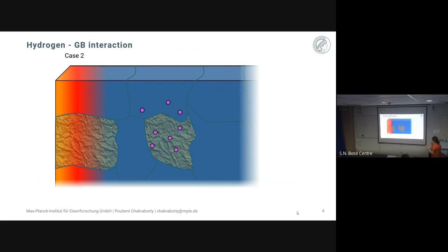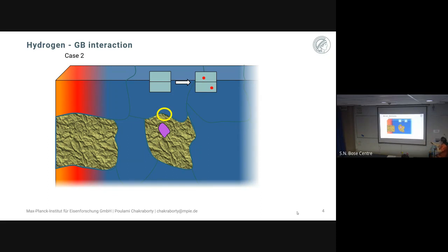Now coming to another case, let us assume that these solute atoms are dissolved in a solid solution. Then they come together and form solute clusters, which happens a lot of the time. But we will be focusing on this grain boundary again, and we are seeing that there is a depletion of solute atoms here, because the solute atoms have formed a cluster somewhere else, far from the grain boundary. Now, if there are hydrogen atoms in the vicinity, this is another case which shows that in presence of hydrogen, it is also wanting to go and sit at the free surface, but without the effect of solute atoms here.